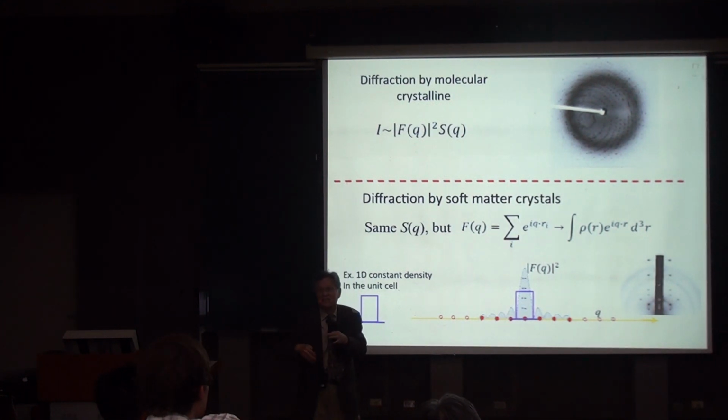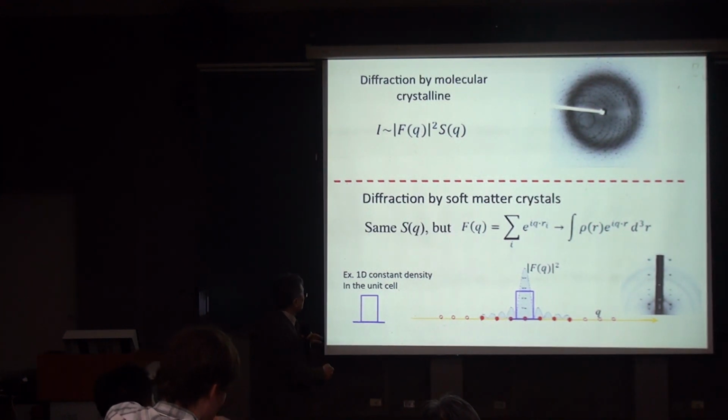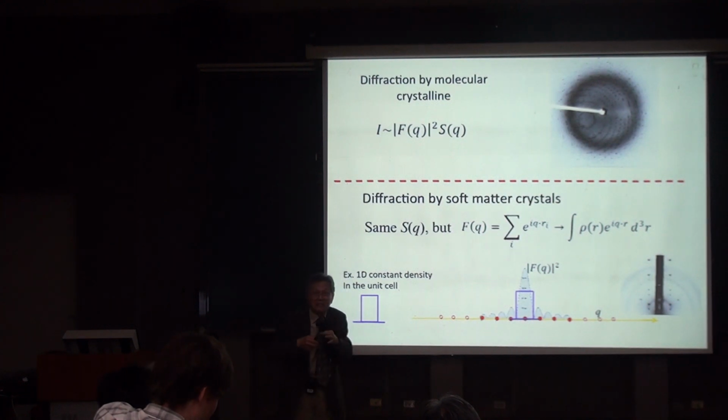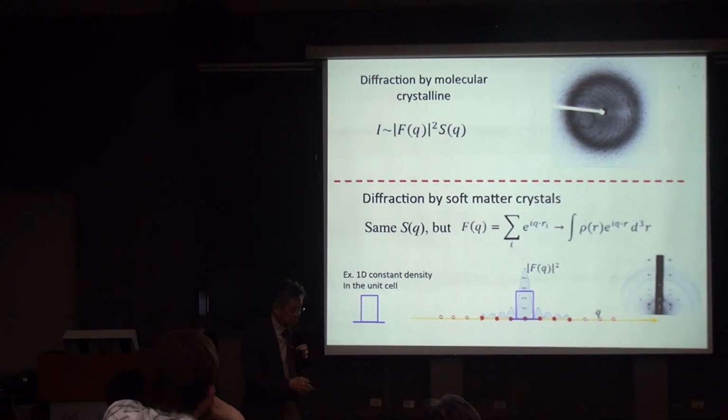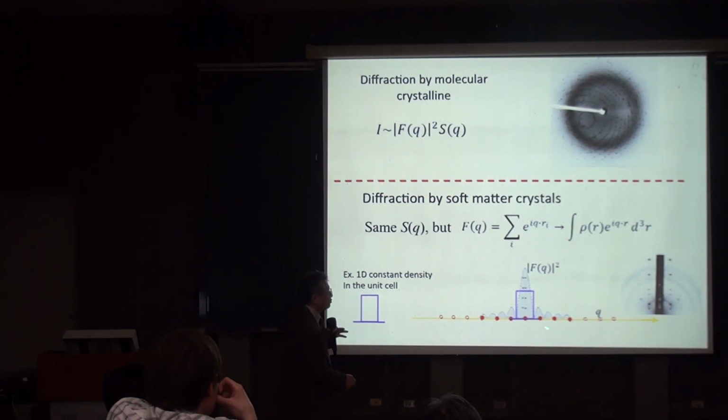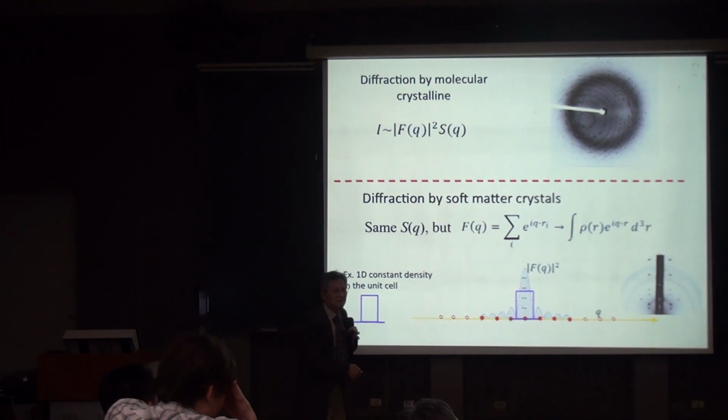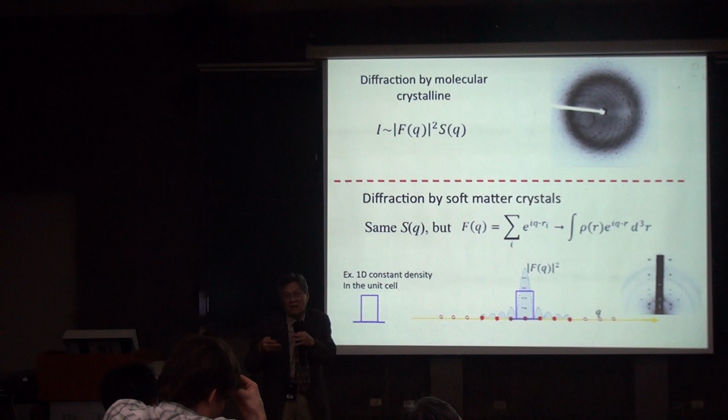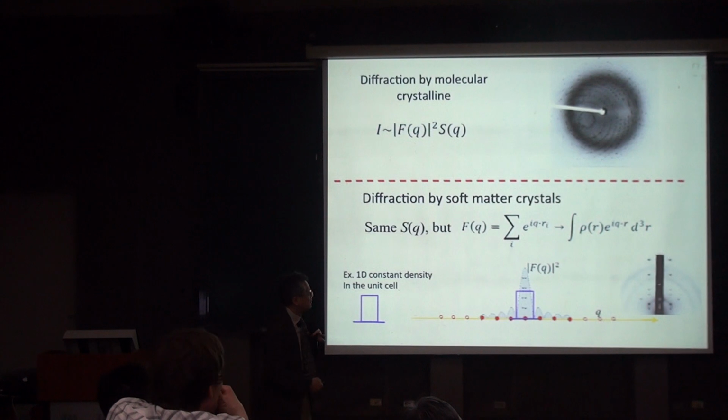Diffraction is the Fourier transform of the real space distribution. So if you Fourier transform a continuum unit cell, you get a broad Gaussian that damps out. So you're limited to a finite range of diffraction peaks, so you have a small number of diffraction peaks. That's fine. There's nothing wrong. If you are doing soft matter, that's a bona fide diffraction pattern.